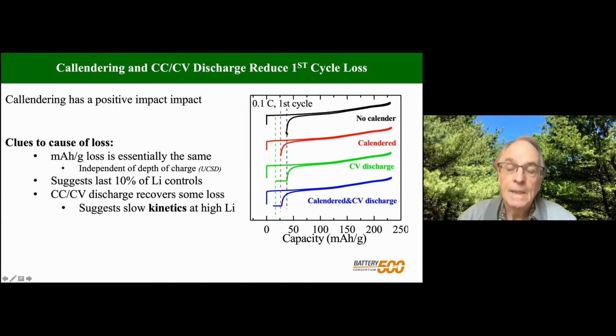So this is suggesting that slow kinetics is the problem at high lithium contents. And I should emphasize Ping Lu at San Diego has studied the impact of taking different amounts of lithium out, and it makes essentially no difference whether you take out 80%, 70%, or 50%, you get exactly the same first cycle loss. So it's the last 10% of the lithium, so above, say, 85% lithium content, that controls everything.